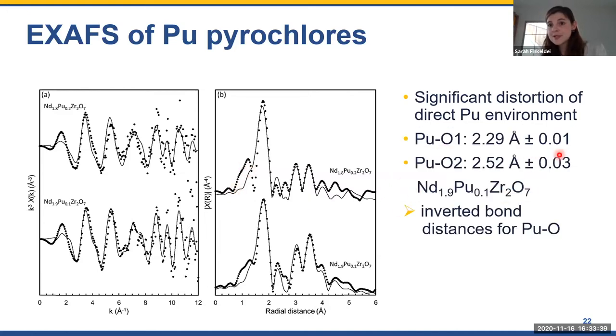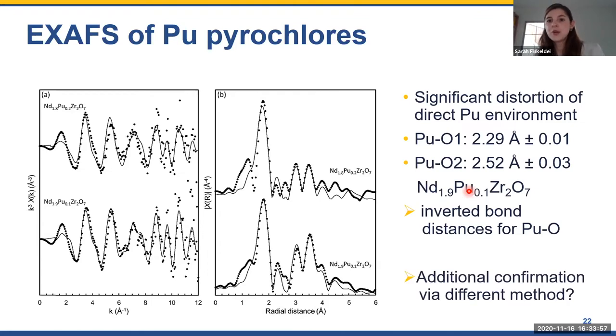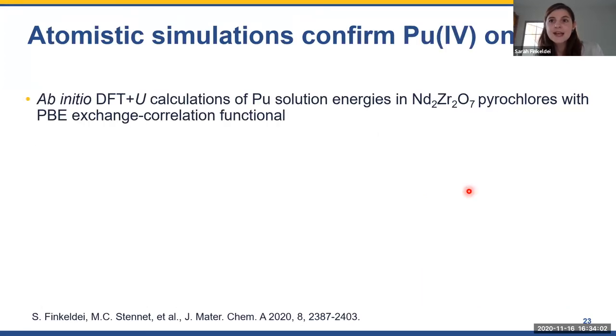What we found is two different bond distances for plutonium and oxygen, and we actually found inverted bond distances. So if you remember, the two oxygens that were in the beginning closer to our cation were now pushed further out. So we definitely wanted additional confirmation with a different method for these surprising results. I asked my computational colleagues again if they could help us out with ab initio DFT plus U calculations to derive plutonium solution energies in neodymium zirconium oxide.